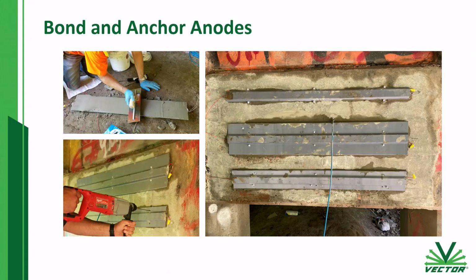And this is one of the early pilot installations. We use different size anodes here, but the idea is that you put a mortar on the back. It's a special mortar that we have that creates the bond between the anode and the concrete surface. And it also is the electrolyte that allows the current to flow from the anode to the reinforcing steel.